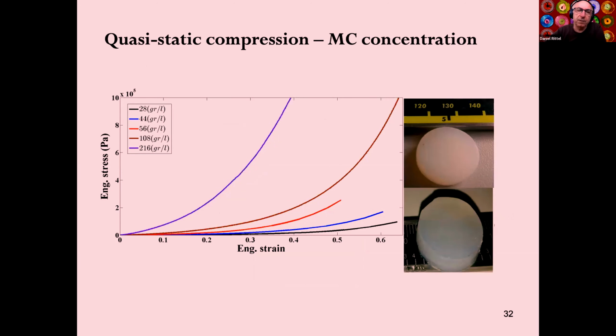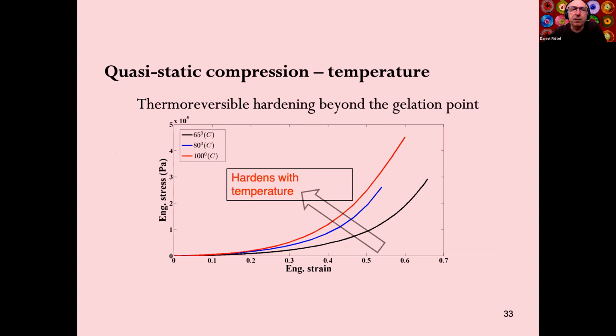Quasi-static compression as a function of concentration. We had yesterday a nice presentation by Professor Alan Zender, who was discussing the mechanical properties of hydrogels. So these are other mechanical properties of other hydrogels at various concentrations in the solid state. Well, the material hardens with temperature. That's again something that we materials people or mechanicians are not really used to seeing, that as you increase the temperature, from 65 to 100 degrees, your material becomes stronger. Of course, don't push much beyond because it will become liquid again. But it means that if you're using this material for any purpose and you leave it in the hot sun of Israel those days and you're afraid that something will happen, don't be afraid, it will only solidify and become stronger.